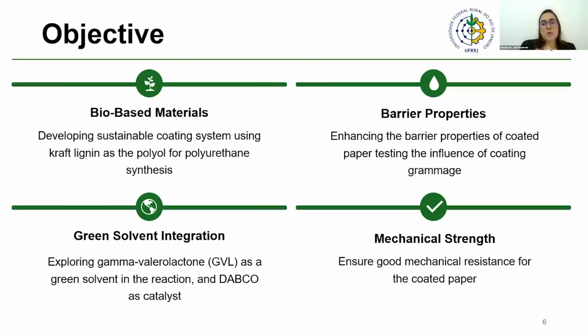In this context, our objective was to develop a lignin-based polyurethane using lignin as a polyol, gamma-valerolactone as a solvent, DABCO as a catalyst, and hexamethylene diisocyanate as an isocyanate source to coat the paper and provide barrier properties while maintaining the mechanical strength. That is one of the most difficult things when you think about the mechanical properties of plastics and the mechanical properties of paper.